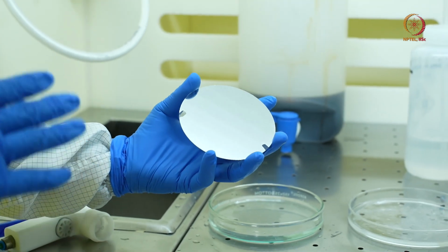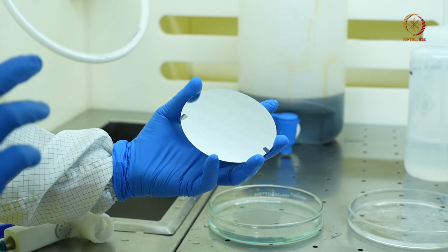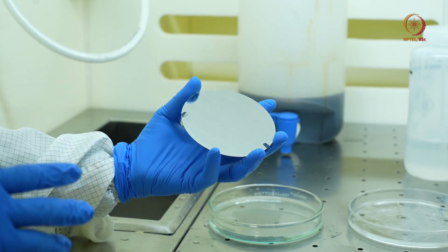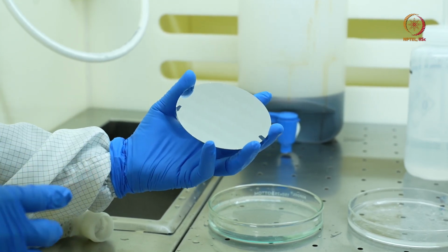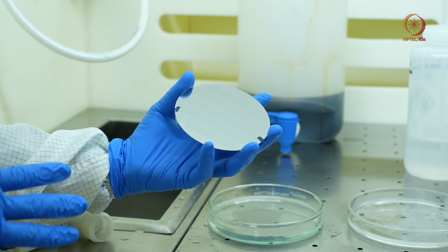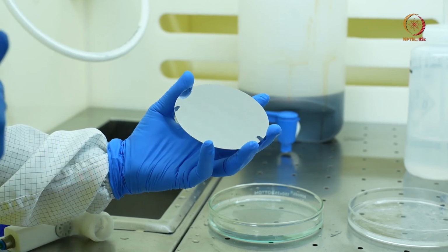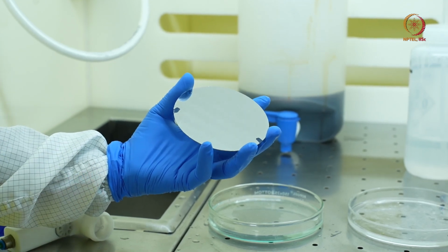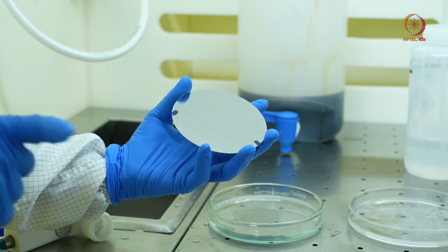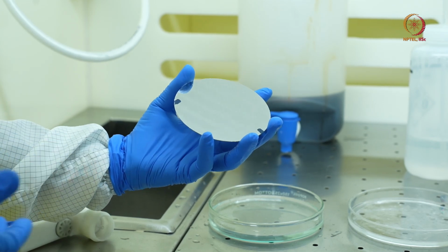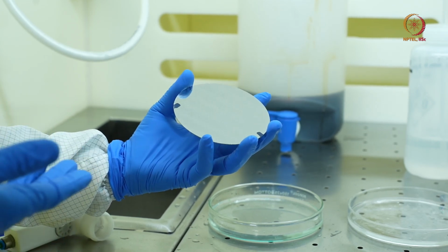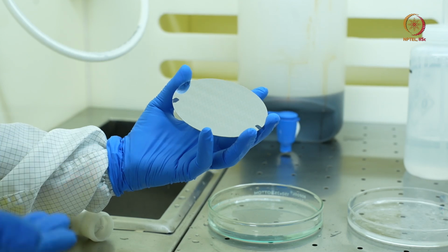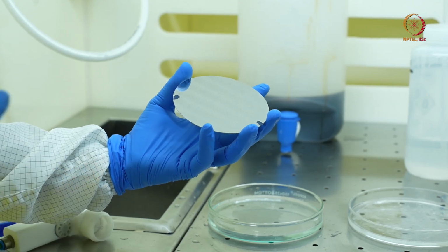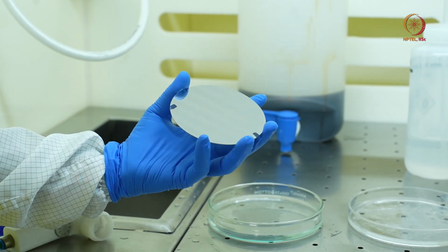Now, on visual inspection, my sample looks dry, but it is possible that there still might be some moisture. So, before going to the next process, the first step would be to keep it on a dehydration bake, where we will use a hot plate to heat our sample at an elevated temperature for a few minutes, which will ensure that all the moisture is dried up.